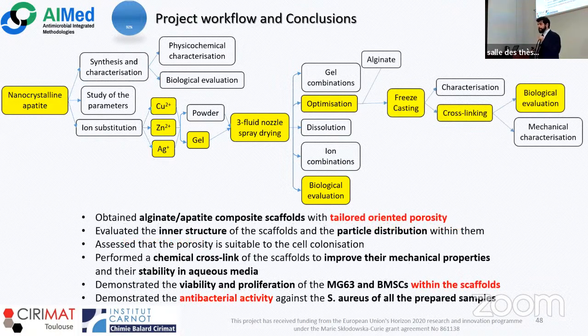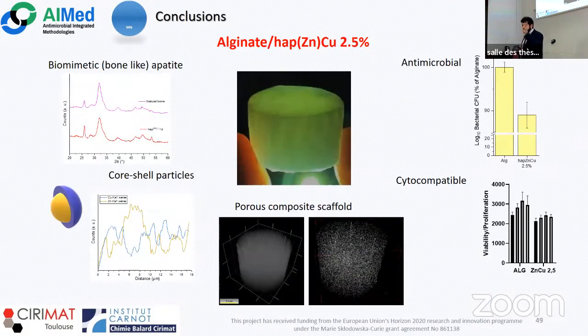And then we obtained some alginate apatite composite scaffolds. We tailored the oriented porosity, evaluated the inner structure, and performed a chemical crosslink of the scaffolds to improve the mechanical properties and the stability in aqueous media, and also demonstrated that they are cytocompatible and antibacterial against Staphylococcus aureus. A good synthesis of all that we have done is the sample alginate apatite zinc copper 2.5%, because it is core shell, it has a porous structure, and it is, of course, cytocompatible and antimicrobial.